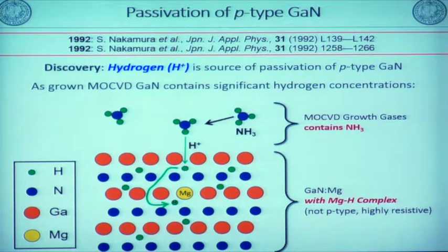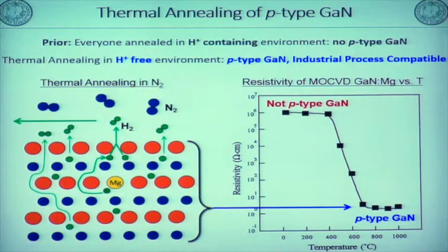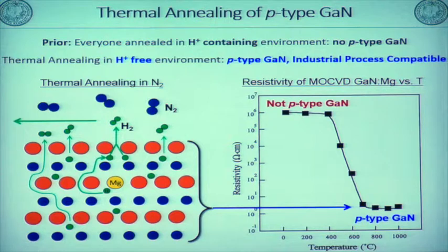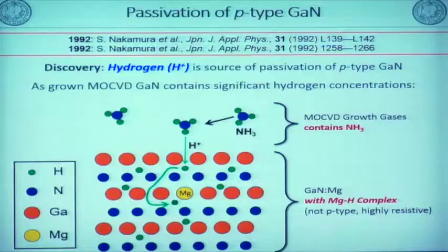The next invention is P-type gallium nitride. This is the key. This is as-grown magnesium doped GaN. As-grown magnesium doped gallium nitride should be P-type, but it was always semi-insulating. Nobody could understand. But in '89, Professor Akasaki and Amano found that if they irradiate magnesium doped GaN with an electron beam, they got P-type gallium nitride, meaning low resistivity P-type gallium nitride. But they couldn't understand the reason. But I could clarify the reason in '92.